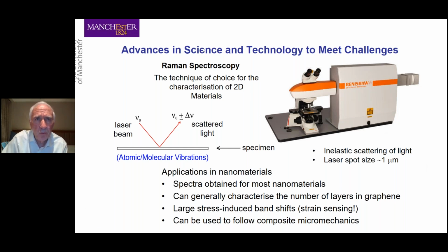And this is something we've been doing for quite a long time, using Raman spectroscopy for measuring strain, and I'll show you how that can be used and probably would lead to a new type of strain sensor. Raman spectroscopy, as most people probably know, is an interesting technique, very useful for 2D materials. You take a laser beam, you focus it onto a specimen, and you look at the scattered light. The laser spot size is about 1 micron, which is important. And you can get Raman spectra from most nanomaterials, particularly 2D materials.